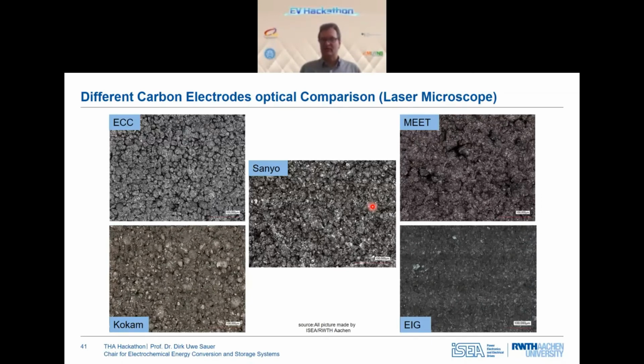Very small particles, for example, give lots of surface and therefore higher rates in charging or discharging. But unfortunately, also the main aging processes take part on these surfaces. So the higher the surface is, the faster the battery ages. So as in many other cases, to find the right composition is a question of compromises among different features, such as charging or discharging rates on the one hand, or lifetime and aging on the other hand.